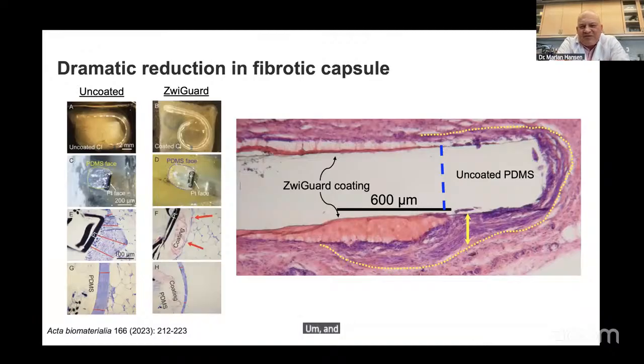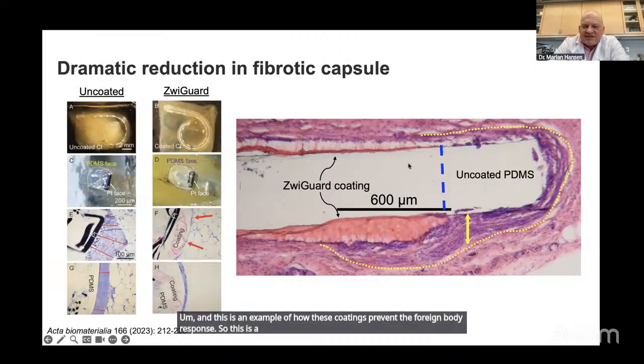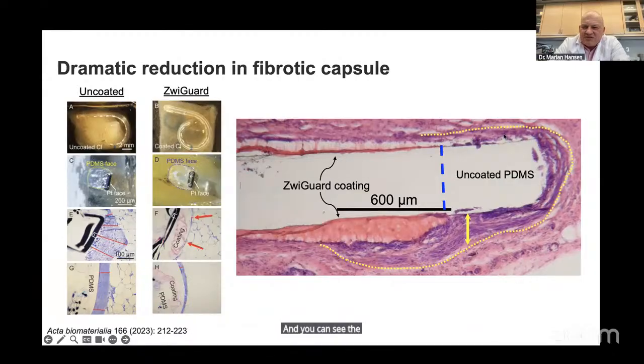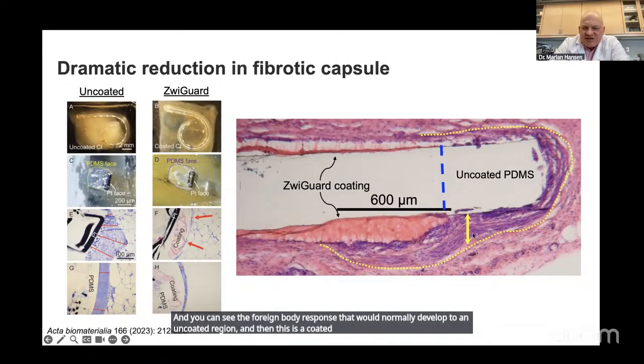And this is an example of how these coatings prevent the foreign body response. So this is a piece of silastic that's placed in an animal for a year. And you can see the foreign body response that would normally develop to an uncoated region. And then this is a coated region. You can see that it almost completely eliminates this fibrotic inflammatory response if you're looking out over here. And that happens too when we do it in cochlear implant arrays, we see that dramatic reduction in fibrosis, even out to a year.